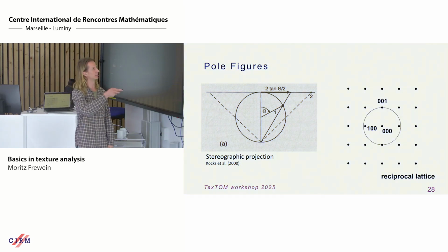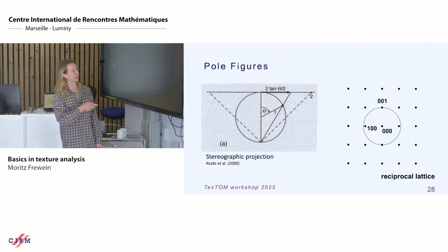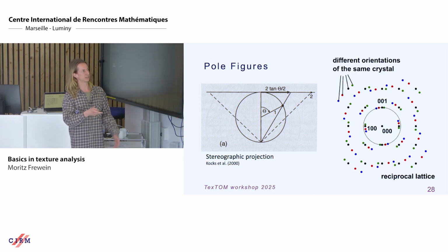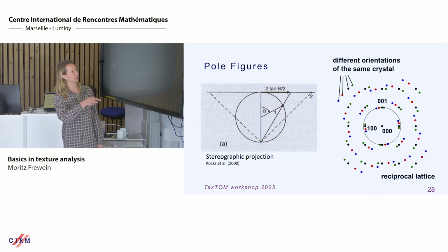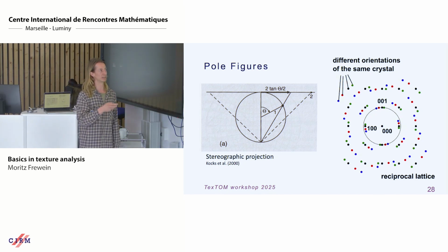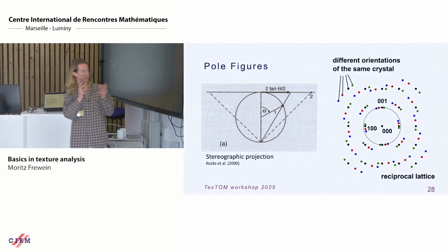And what is actually this sphere in our experiment? Again, we have the reciprocal lattice, and we draw a circle around a Q value where we find a peak, for example. So we would find maybe these two here, but if we have a texture sample, then we might have several orientations, and we find a spot composed of all these peaks that lie on this Q value.